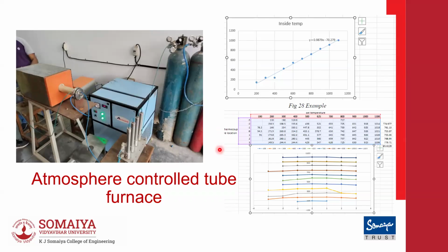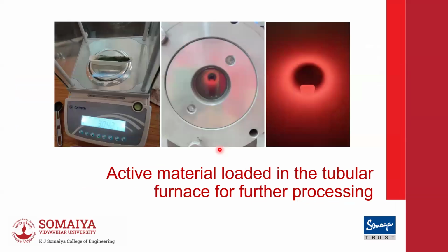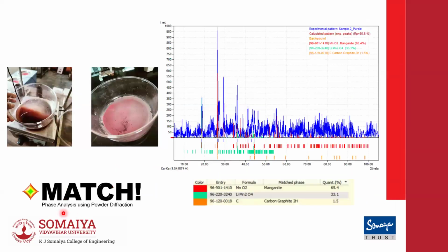These are some of the calibration curves that we got. We need to identify the uniform temperature zone where I need to put the samples. So this is basically that activity. We put the black mass, weighed the amount of black mass in an aluminum crucible, put it in a boat, and then put it inside the furnace. We did a match, which is basically similar to an XRD analysis. We found that we have around 65.4% MnO2 for this pink salt that we obtained, and 33% is lithium salt. So the next step is to try to separate these two.